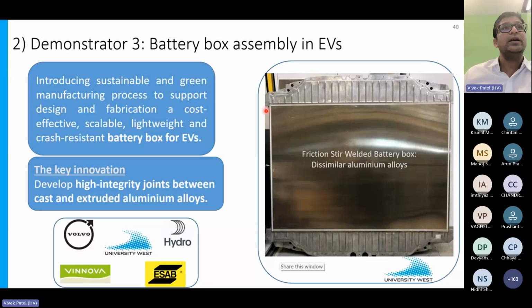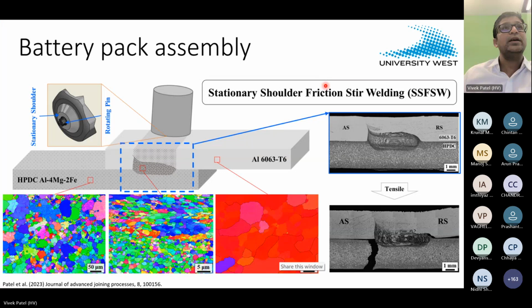So we wanted to understand whether this sheet metal to cast aluminum can be welded in lap joints and what the joint integrity is. So we optimized the process by having the sheet metal on the top and the high pressure die casting on the bottom, and you can see the typical cast structure in a weld cross section. That's a dendritic structure, and on the top you have the extruded material.